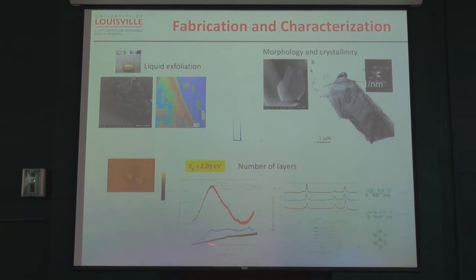If you look at the photoluminescence, you don't see a big photoluminescence peak until you get to monolayer. The bulk and few layers don't show strong luminescence, but monolayer phosphorene shows a band gap that comes close to 2 electron volts, like we expect for the monolayer.